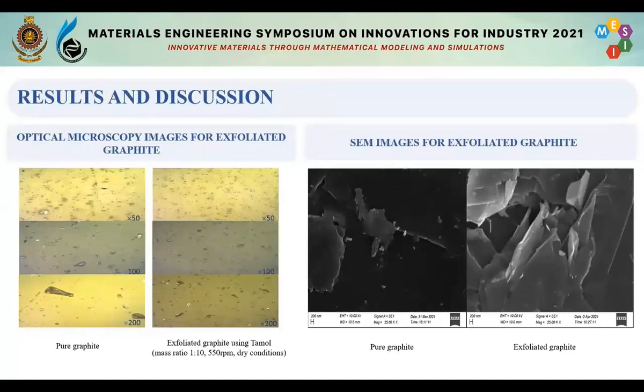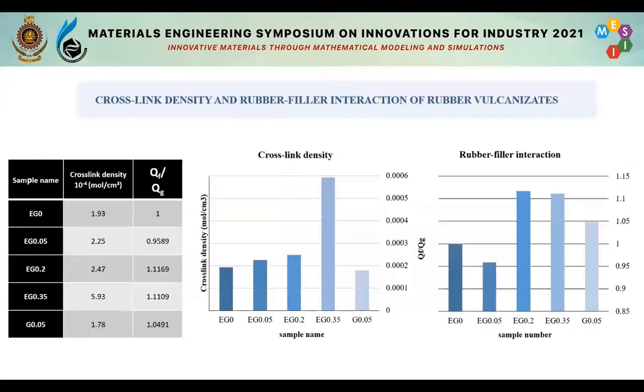Here we have plotted the calculation results of crosslink density and rubber filler interaction using the swelling test. Crosslink density of rubber vulcanizate has been increased with the increased amount of exfoliated graphite being used, which directly affects the mechanical properties of the final rubber vulcanizates. When it comes to rubber filler interaction, usually if the rubber filler interaction indicator is higher than 1, it is to be said that the rubber filler interaction is lower.